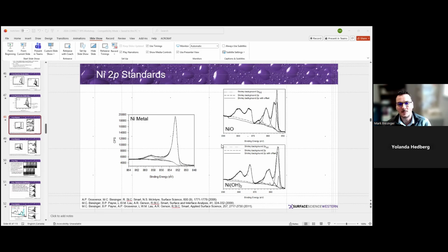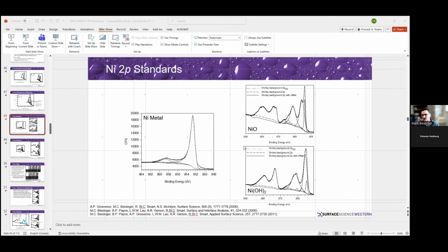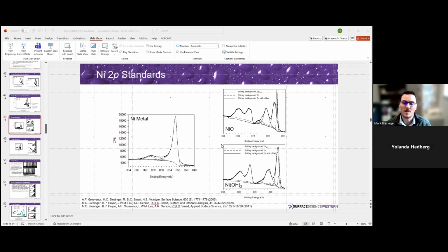XPS mapping. As we go smaller spot size, the data peak distortion increases. Do you have any recommendation to collect good data for mapping for a spot size of 10 to 20 microns? That can be instrumental in nature. And so there's two types of instruments. There's a microscope type analysis and a microprobe type analysis. So the Kratos and the Thermo instruments, when they do imaging, they're doing a microscope type analysis.